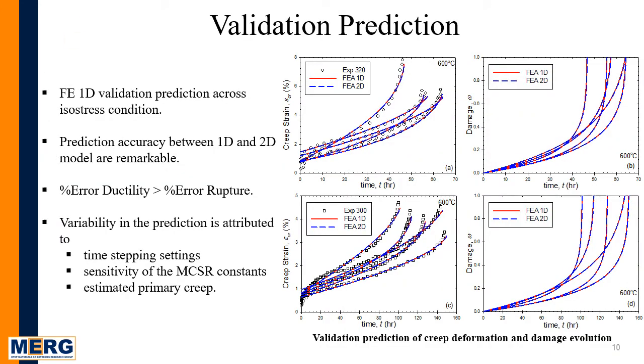In this slide, the validation predictions for the 1D and 2D models are shown across isostress conditions. Looking at the plots, the comparison between the experiment and the prediction is quite satisfactory. On further analysis, we can see that the 2D predictions almost superimpose on the 1D predictions. And analyzing the graphs, we can say that the percentage error in ductility prediction tends to be more than the percentage error in the rupture prediction. This variability in the prediction is attributed to the time stepping settings, the sensitivity of the minimum creep strain rate related constants, and the estimated primary creep.